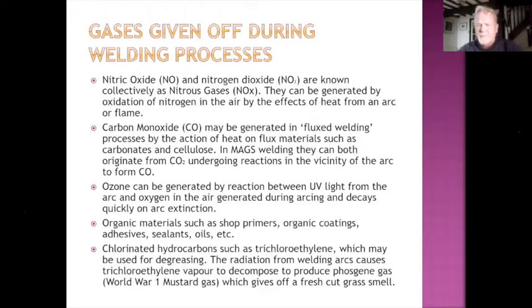Ozone can be generated by the reaction of the ultraviolet light from the arc with oxygen in the air, but it also decays quickly upon arc extinction. There are organic materials such as shop primers, organic coatings, adhesives, sealants, oils. These can all generate some fume, although there have been some developments now whereby you can get weld-through primers. These have taken into account the potential for the fume, and they've reduced the content and increased the conductivity of the coating. So for people working on classic car restoration or whatever, they may well prime it and then they can still weld onto that coating.